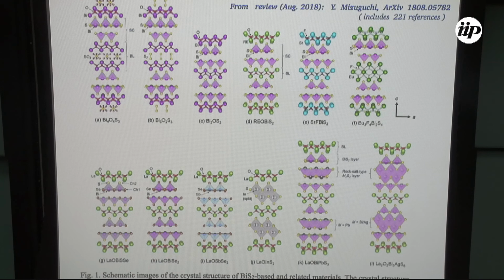And more recently, there have been also some other kind of doping in which they are doping into the sulfur, and, for example, including chalcogens, like selenium. And what they found is that the superconducting properties are not affected too much, but by putting that kind of doping, they can obtain functional materials with nice thermoelectric properties. So that's also some interesting detour from these materials and possible applications.